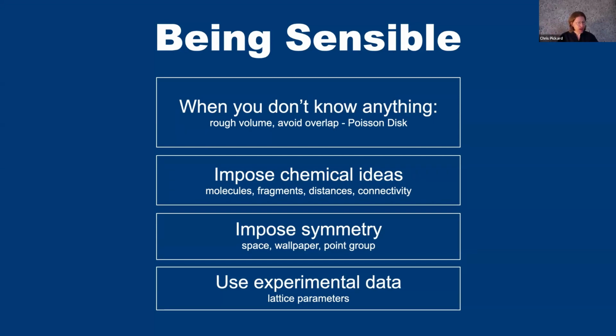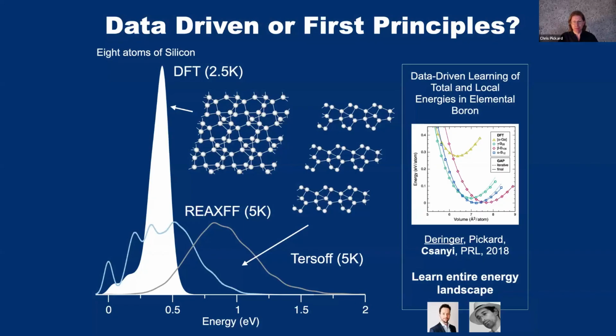And the other powerful constraint, and this is probably appropriate for this group, is the combining of experimental data like we did for the boron example with the searches. Because this, again, can massively reduce the size of the space you have to search for your solution. If you know what the lattice parameters are, or you have some other constraint on your system, that can speed things up considerably.